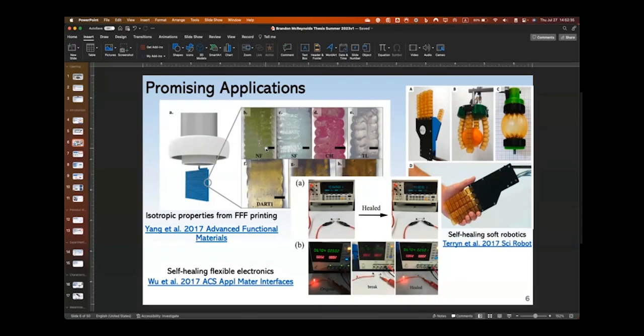But what's the major roadblock? The major roadblock is the maleimide self-reaction, I would say, because ideally you want these materials to be recycled multiple times, or printed multiple times by taking them to the retro-Diels-Alder temperatures. But as I hope I've shown today, with that self-reaction of one of the main reagents, there's a practical limitation to how long you can use these materials.